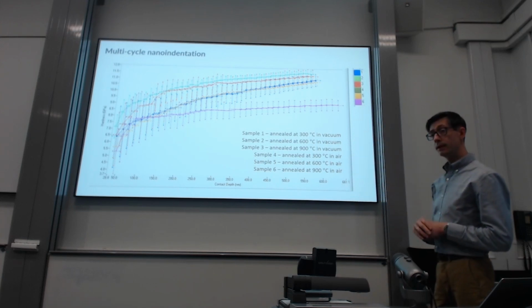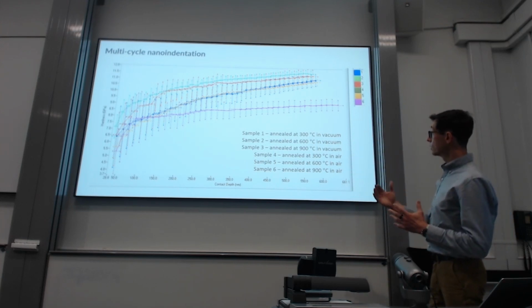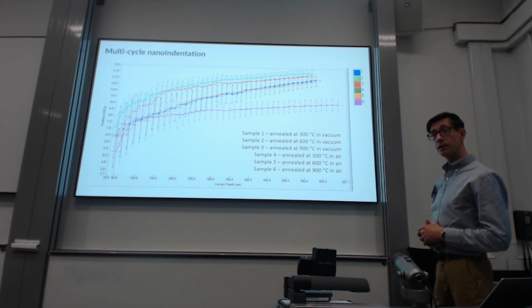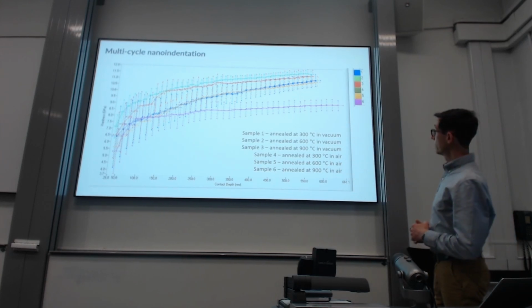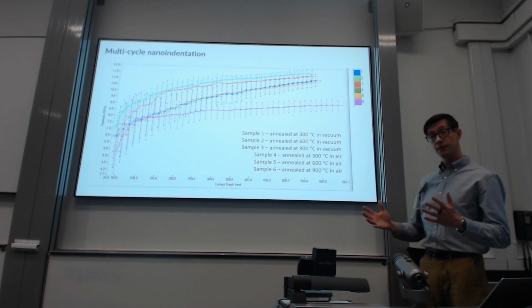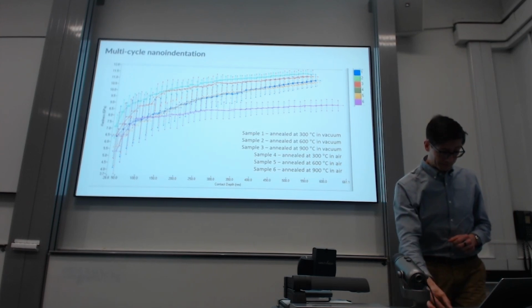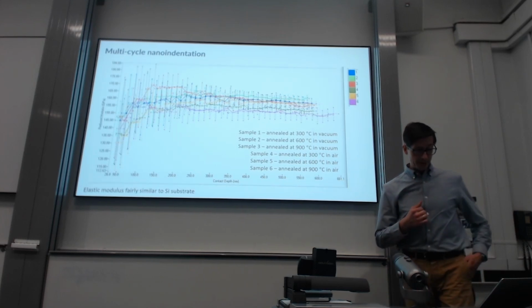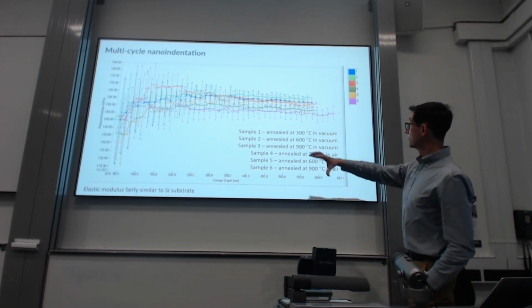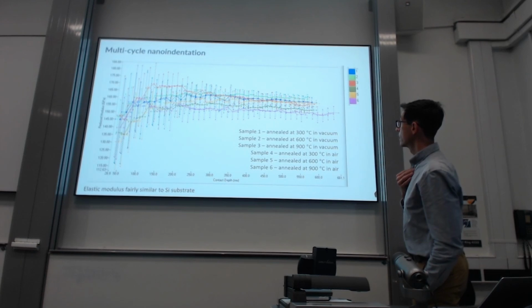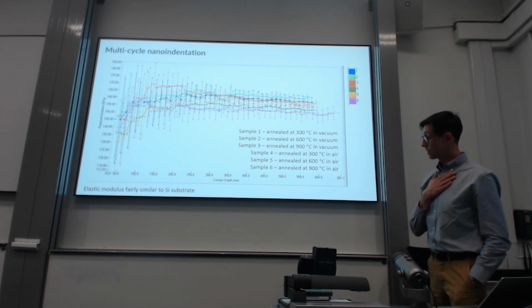So this is not a single point. You have 40 indents clearly showing the trend in terms of hardness as a result of depth. So that's the result we have for that sample. And in terms of elastic modulus, fairly consistent results around 155 gigapascal.